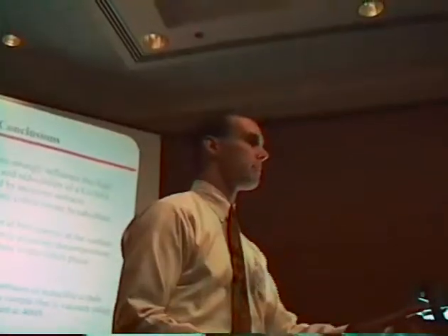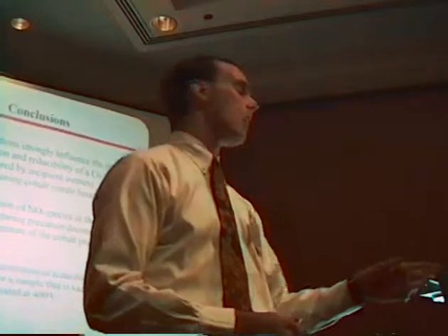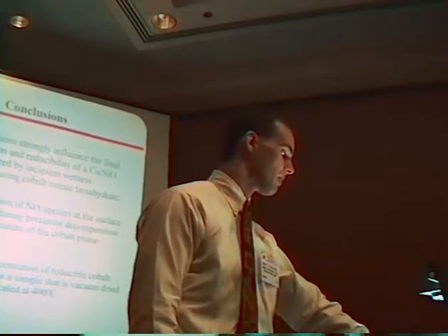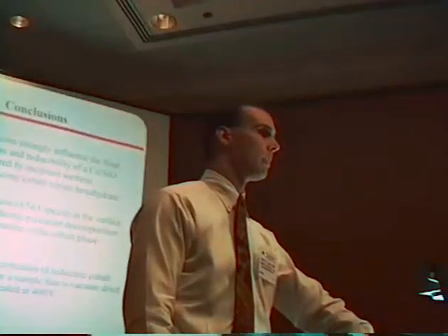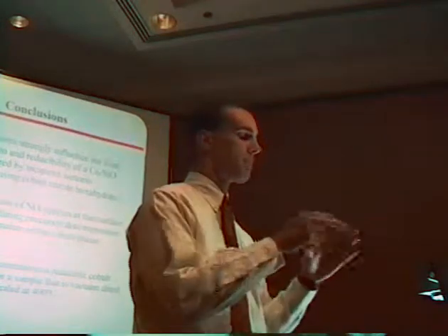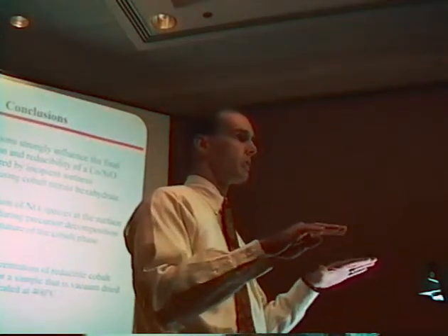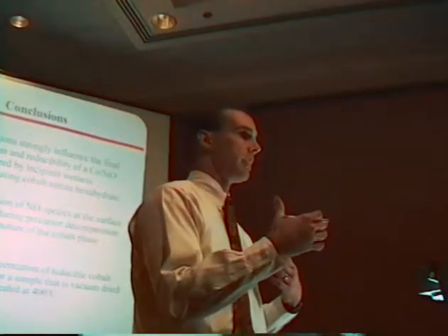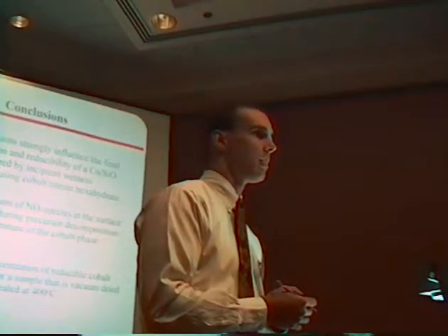Yeah, John? What's NOx doing? What's your thought about that? Is there something magic about NOx, or could some other anion do this? That's something that we're investigating using different types of precursors. The way that we came onto this idea was based on some work done on cobalt on alumina, where they suggest that the dispersion of the cobalt on the surface of a support is determined by whether or not it can be oxidized during the decomposition process.